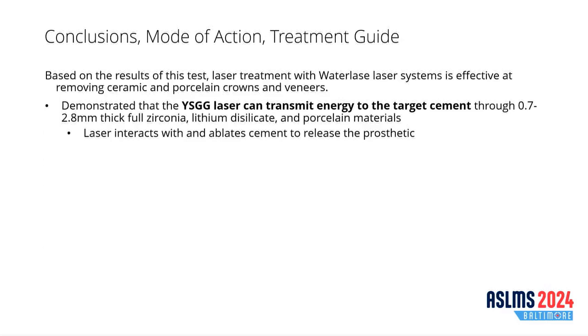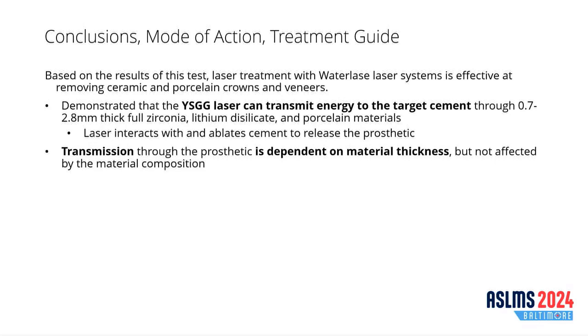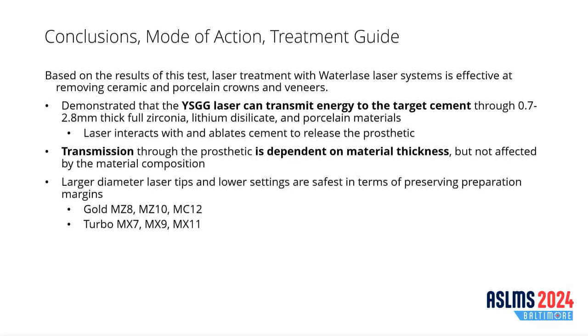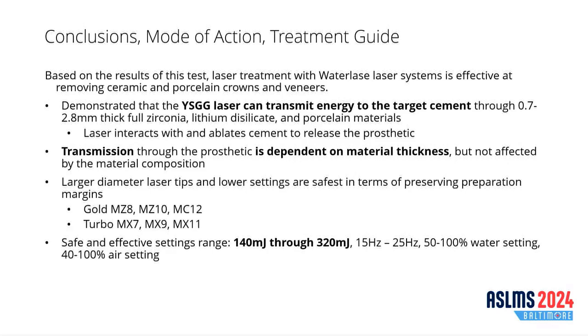So the way this works is erbium lasers can transmit all the way through the prosthetic. They interact with the cement and start to ablate it. The treatment depends on the material thickness, so the thicker it is, the longer it might take. You want to stay with the lowest settings, and our safe energy and setting range is 140 millijoules to 320 millijoules at 15 to 25 hertz. And you want to use as much water and air as you can to keep the area cool.